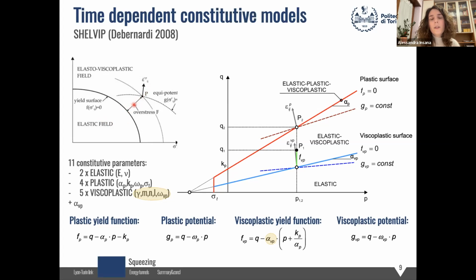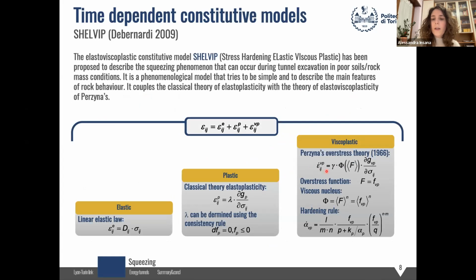So it's called overstress theory because it's a measure of the overstress, so the distance of the stress point from the yield surface. So the viscoplastic strain rate is expressed as a function of the so-called fluidity parameter, the viscous nucleus, the overstress function, and the viscoplastic potential function. The overstress function is assumed to be equal to the viscoplastic yield function. So the viscous nucleus is given by F_VP to the power of n in the so-called Macaulay brackets, so that if F_VP is negative, the viscoplastic strain rate is equal to 0 because we're in the elastic domain.